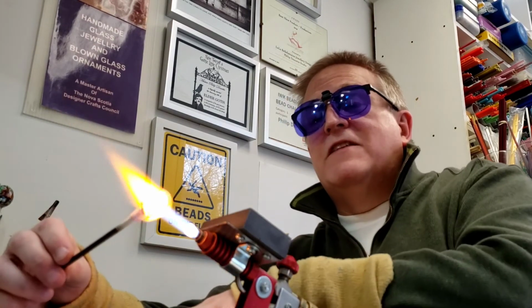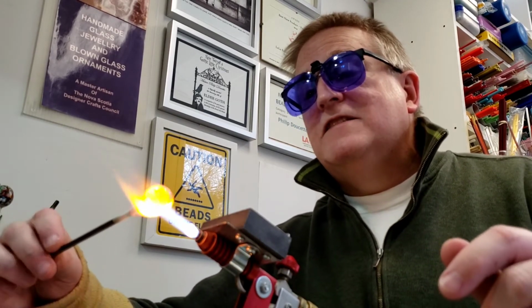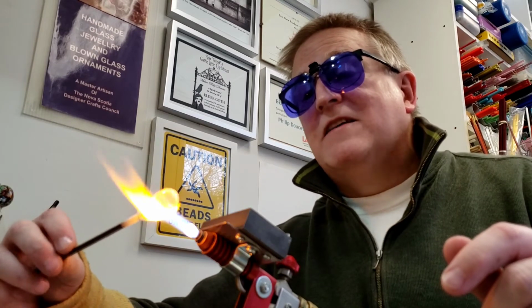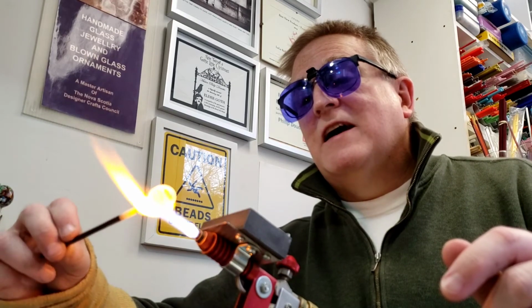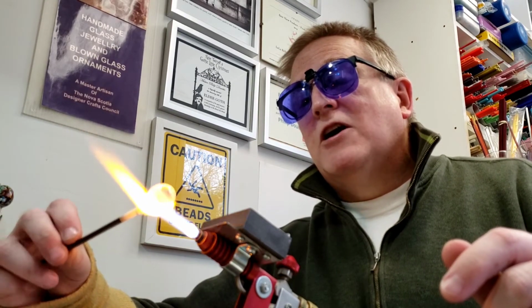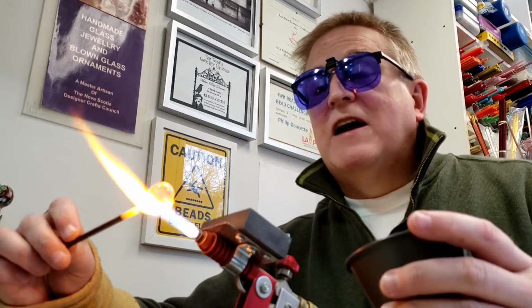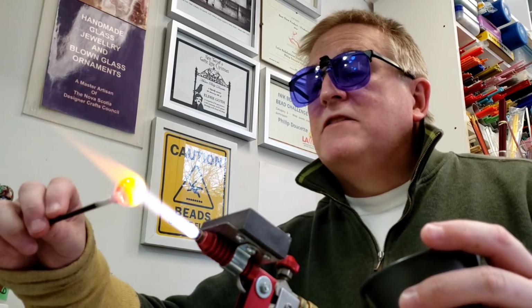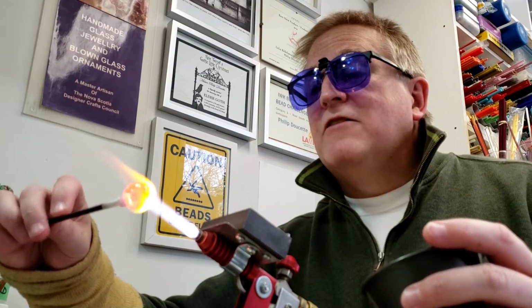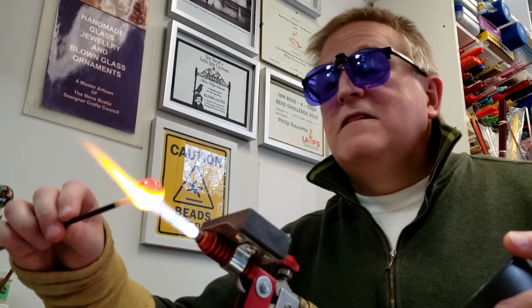And that's one of the things that catches people up when working with glass, because it is actually fairly easy to break up bottles and just make beads out of them. When you want to start mixing glass together, though, you have to use glasses that are very similar in their coefficient of expansion, which is actually their coefficient of contraction as well. Because if you don't, the glass will crack and shatter when it reaches a certain temperature, a lot of people get put off the idea of working with glass. I didn't, and here I am today.